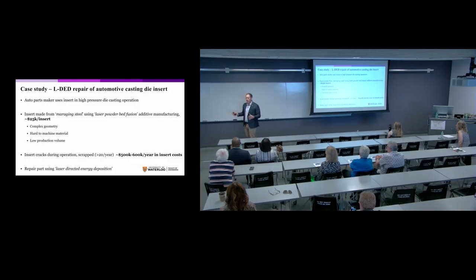And that's great. The downside is that it becomes very expensive. So it's about a foot long, weighs about 40 pounds, but it costs them about $25,000 to produce a single insert. And so when I talked with the company, they told me that after a few thousand casting cycles, this tooling cracks. And when I asked them, okay, what do you do with that? They said, well, we throw it in the bin, get a new one. I said, okay, how many times does that happen? They said, about 20, 25 times a year. So you do the quick math, that's about $500,000 to $600,000 a year in operating costs from a single casting operation. So I told them, send us the insert, send us a damaged insert, and let's see what we can do with this, okay?